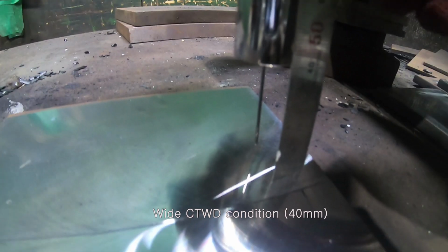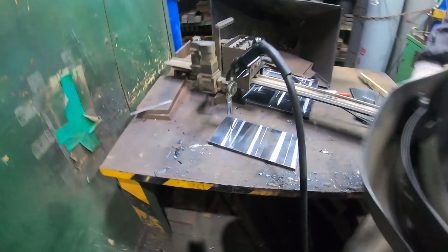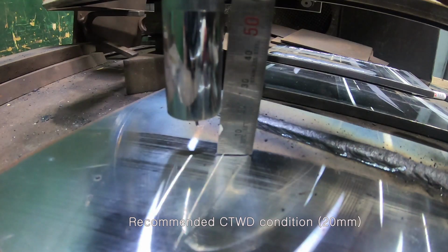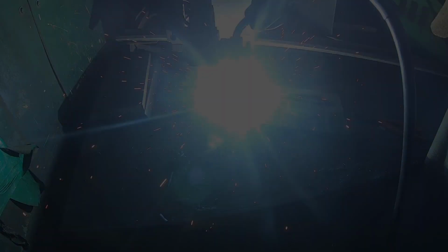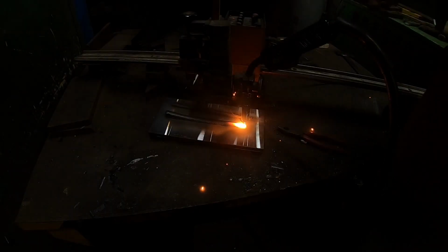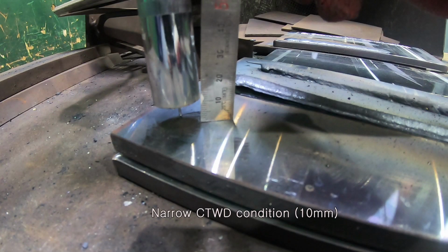The wider CTWD reduces the current, resulting in thinner penetration, higher overlap, and shaking arc balance, resulting in high spatter. When the CTWD is narrow, the current increases to deepen the penetration, increasing the melting of the welding material, reducing the straightness of the beads, and increasing the convex beads.